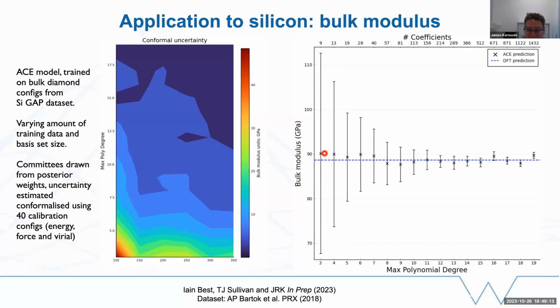And what we see is that the models improve, the mean accuracy matches the target a little bit better as we go on, but also the error estimates improve. And what's really nice is that because we've used this conformalization approach, all the error bars cover the true result. So the DFT result for the bulk modulus is shown here in blue, and actually not quite all, but most of the error bars are sufficiently large to cover the true result. We have 95% coverage here, which is why the last one doesn't quite cover. That's something that we can actually choose when we set up the approach.